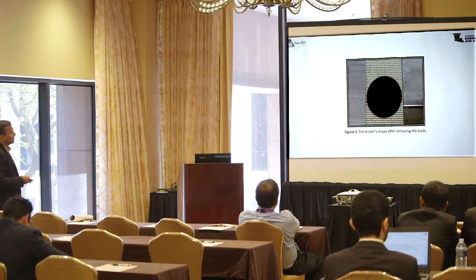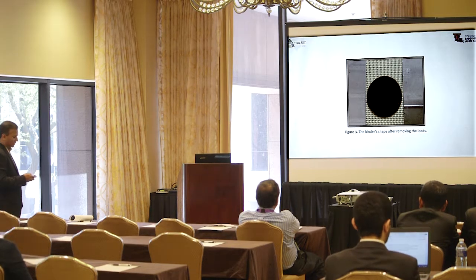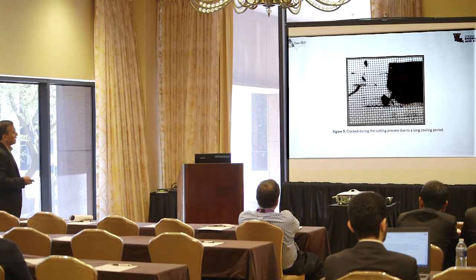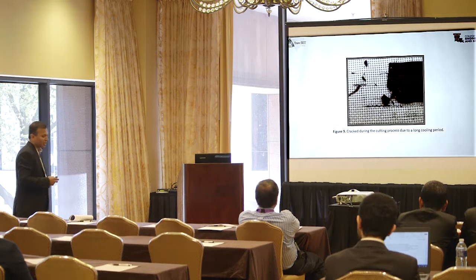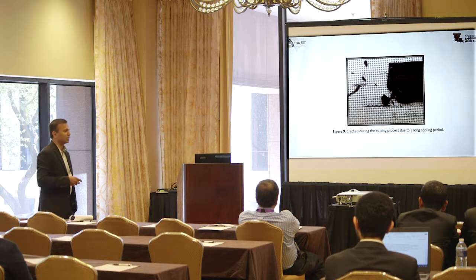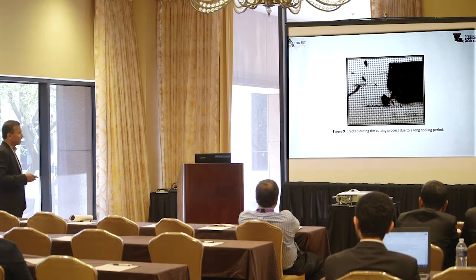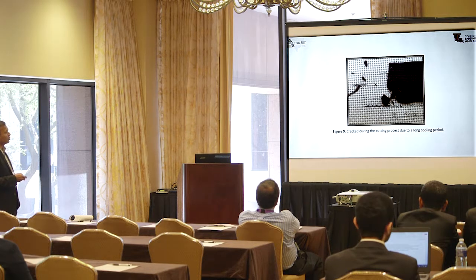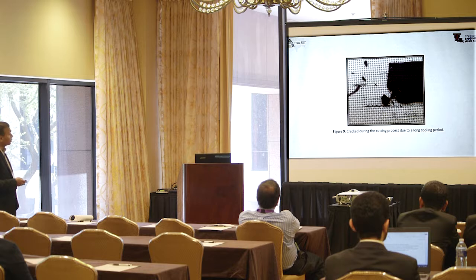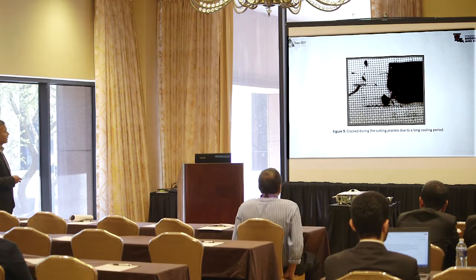The binder shape after removing the load. So this is the shape. You can see that it looks pretty much circular. It came from a DSR mold. And then two pictures, they cracked during the cutting process due to the long cooling period. So now we have to cut the samples. Still we are cutting it manually using a sharp edge knife, and you can see that before cutting it, you need to pull it a little bit. If you pull too long, it will crack during cutting.